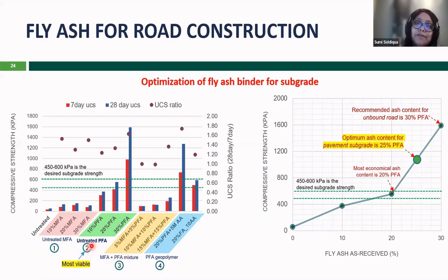These are the most valuable ones because if you don't have to treat them, it's more cost effective for application and easier to use. The third one here is a combination of multi-cyclone and the precipitator fly ash, but it doesn't help much, as you can see from the UCS data. And the last one is the PFA with the geopolymer. As you can see from our untreated PFA, we got very high values for compressive strength for the 28-day sample. And we also see the ratios are very close over here.